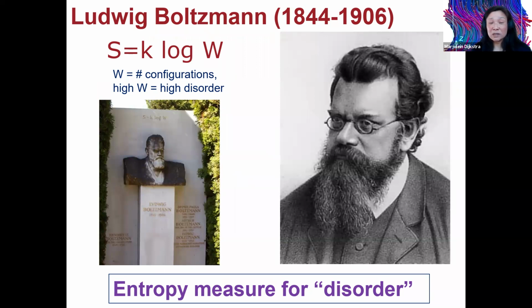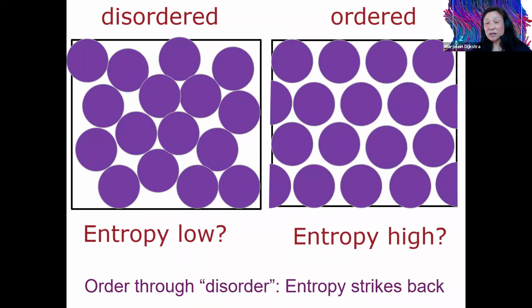it was even engraved on his tombstone, S equals k log W, with W the number of configurations, one can easily see that if you make a schematic picture of a fluid phase at sufficiently high density and of a solid phase also at the same density, one can immediately see that in the fluid phase, all the particles, which are random, are completely jammed with respect to each other, so they can't move anymore, whereas in the solid phase, where all the particles are located at their lattice position, all the particles can still wiggle around their lattice position, and the wiggling room means more configurations, and so the entropy is actually higher for these crystal structures.